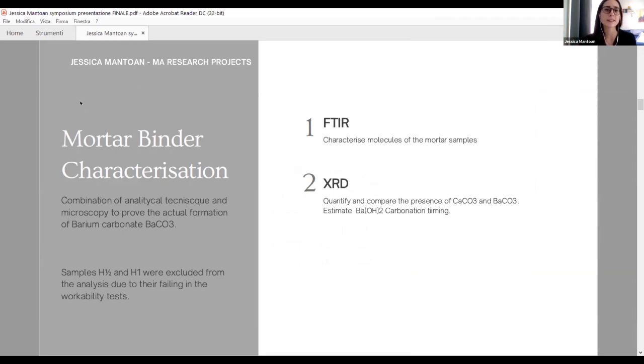And the first thing that I carried out was a study about the binder, in order to understand if the barium hydroxide that I used in preparation was able to carbonate perfectly with the rest of the mortar components. Unfortunately, during the preparation of the mortar, I also carried out the workability test, and I realized immediately that hydraulic mortar containing medium and large quantities of additive was not usable.